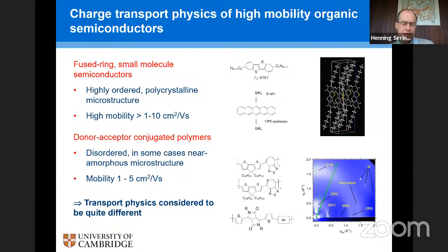And then the second class of system are the conjugated polymers. They are long chain polymeric pi systems, and traditionally they used to have much lower mobilities than molecular systems, because in a polymeric system you tend to have much less ordered structures, more amorphous microstructures. But there have been recent developments that have brought the mobility of polymeric systems up almost to the level of the small molecule systems, and we now have quite high performance polymeric systems with mobilities in the range between 1 and 5 centimeters squared per volt second. And from a technological perspective, polymeric systems have their advantages because they are easier to process. You can achieve higher uniformity over large areas.